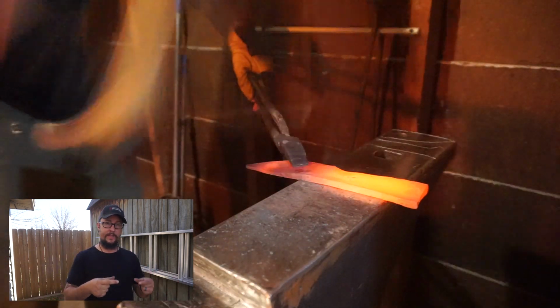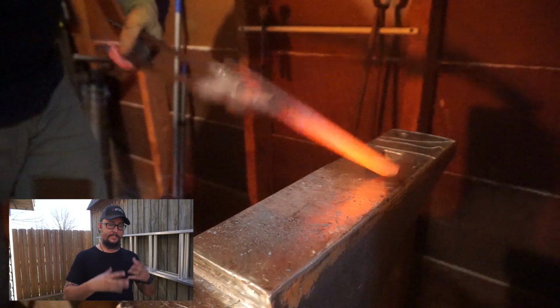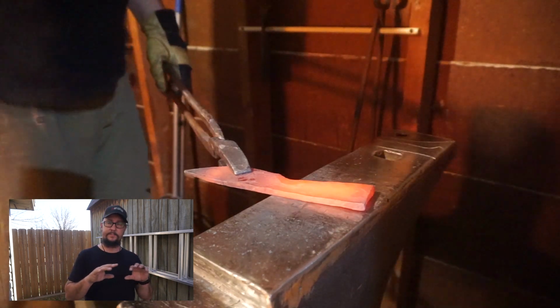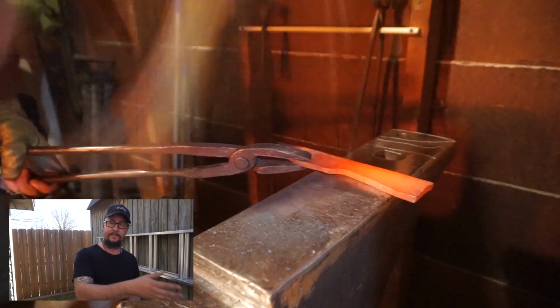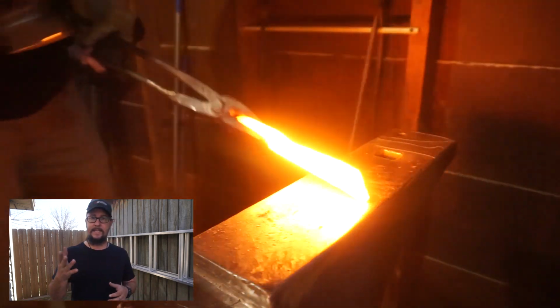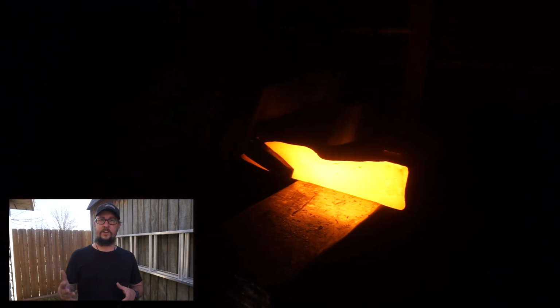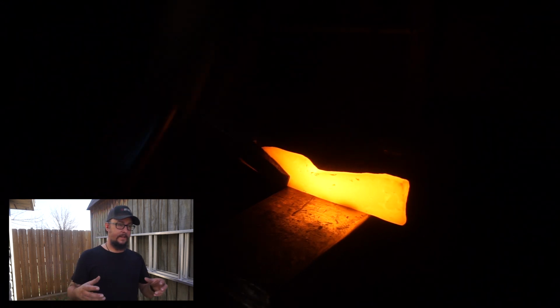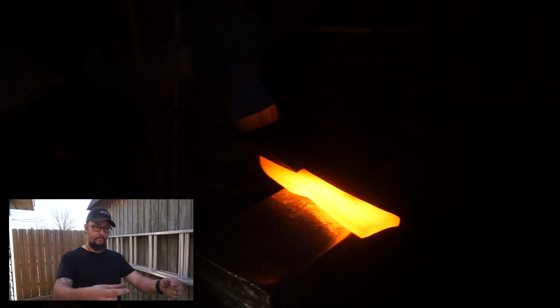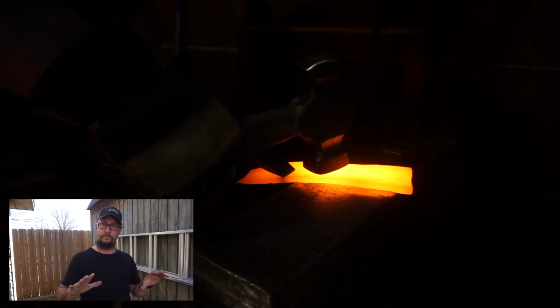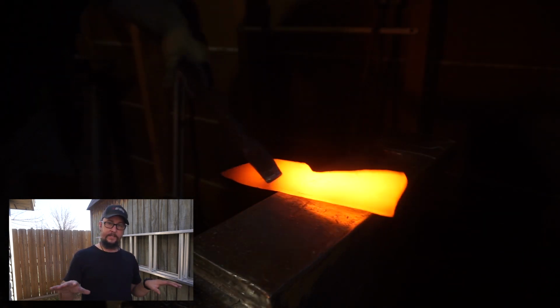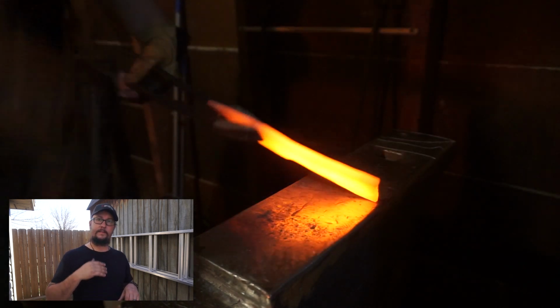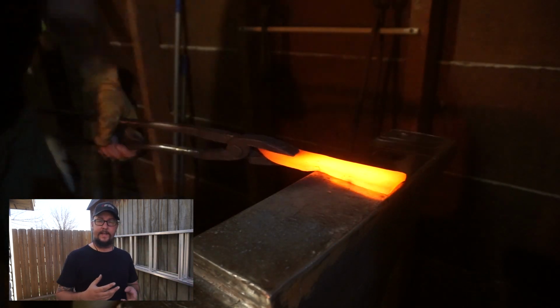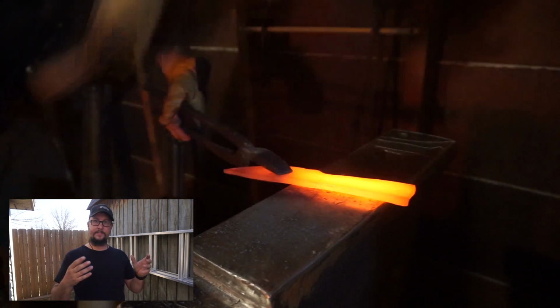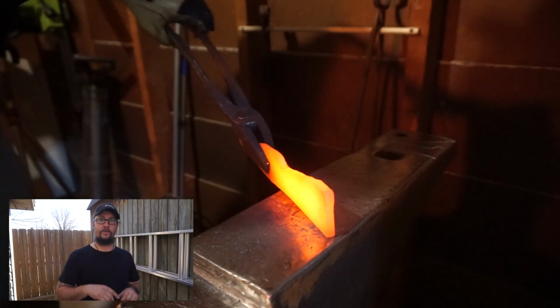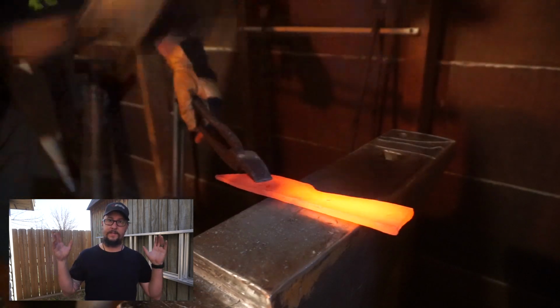I'm letting it cool on the edge of the front of my forge so that it still has a little bit of heat and it can cool down kind of slow, but still not as slow as being inside the forge. And then on the second heat, I'm going to bring it up to about 1500 degrees. And all we're going to do is then again bring it to the edge of the forge, let it cool. And then once it's completely cooled, I'm going to go in 1400 degrees, or about non-magnetic. So heat it up to that point, let it cool, and now my knife has been normalized.